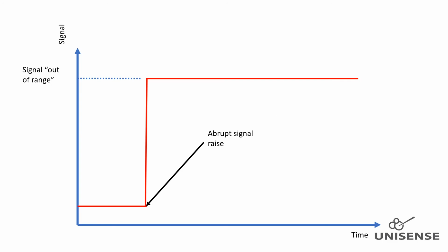I now turn to troubleshooting nitric oxide microsensors which do not exhibit normal performance. Naturally, a small glass tip is fragile and the tip might break if it hits something hard. A broken sensor will in water give a very high signal, typically out of range, as the working electrode is now directly exposed. So, if the tip breaks during measurements, a sharp signal rise will occur to the out of range signal. It is not possible to repair a broken sensor. If the tip gets biofouled or covered with sticky polymers, it might measure incorrectly.